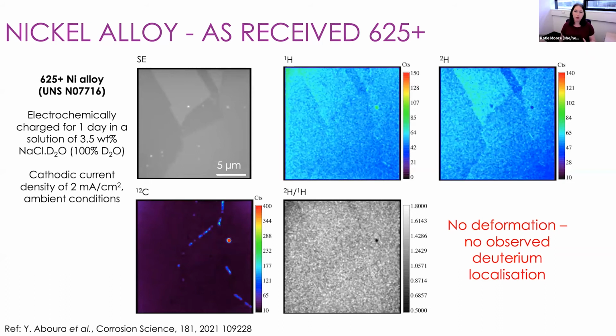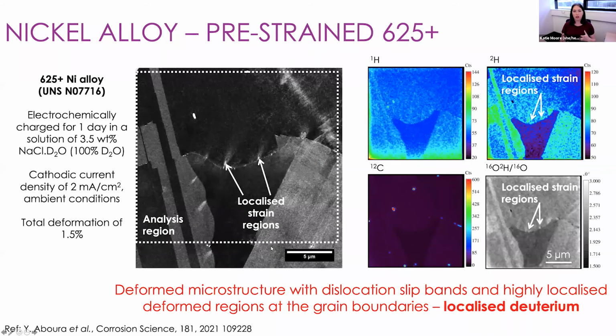Then we increased the complexity of our experiment somewhat. Now we were looking at a pre-strained 625 plus sample. We took our as received sample and strained it to a total deformation of 1.5% to introduce some strain into our material. Here in our backscattered electron image, which was taken before the NanoSIMS analysis, you can see that there are some regions where we have localized strain, specifically at these grain boundaries here. When we look at this exact same region in the NanoSIMS and look at our ratio map, you can see small enrichments of deuterium at these localized strain regions just here.